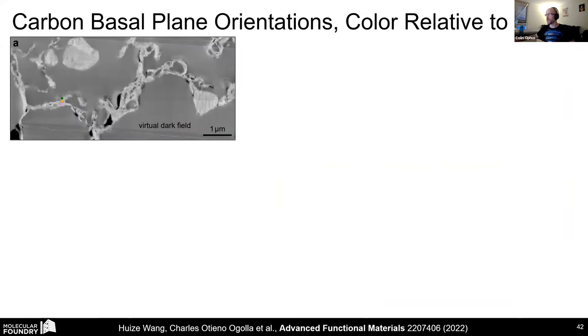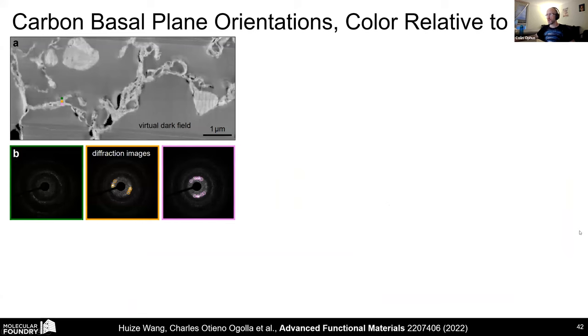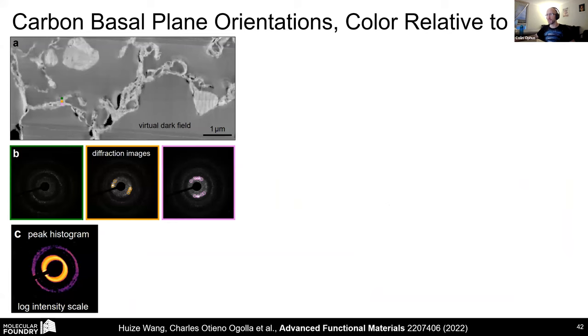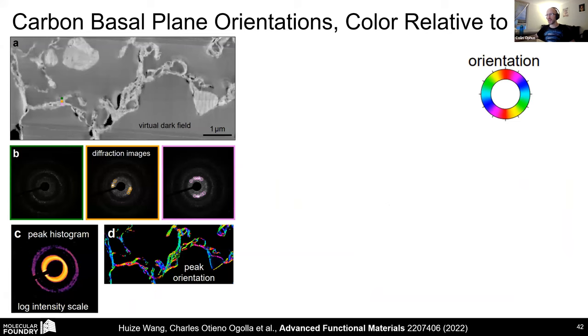So I'll show, I think, one more orientation example I have here. This is an imprinted material that a user brought to us. In this material, we did our full 4D-STEM scan. We measured all the innermost diffraction ring spacings here. This is the basal plane of carbon, and we're able to get an orientation of these carbon basal planes.